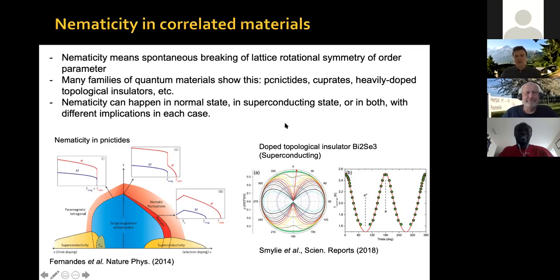Okay, now in doped topological insulators, for example, copper doped or strontium doped, you can dope topological insulators such as bismuth selenide with several materials. They become superconductors, and people have seen that when they look, for example, at TC versus magnetic field direction, they can see that there are two maxima within 360 degrees. This means that the system goes from a crystal symmetry where you have threefold rotational symmetry to a response which is twofold symmetric, has C2 symmetry, meaning an ellipse.